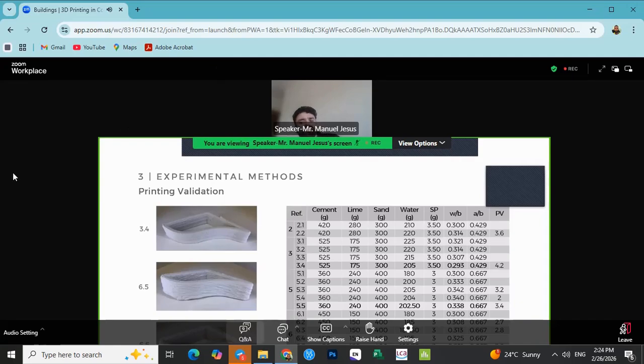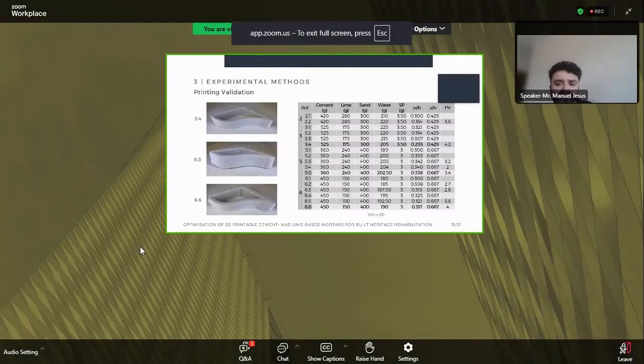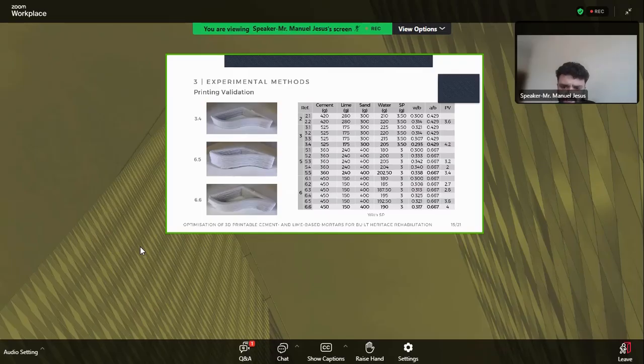The superplasticizer here was added at a dosage of 0.5% of binder mass. And while this admixture allowed for a significant reduction in water content, these mixtures experienced a faster loss of workability, in this case a reduced open time. This rapid stiffening presented a technical challenge because it increased the risk of extruder clogging, and some interruptions during the printing process were observable.